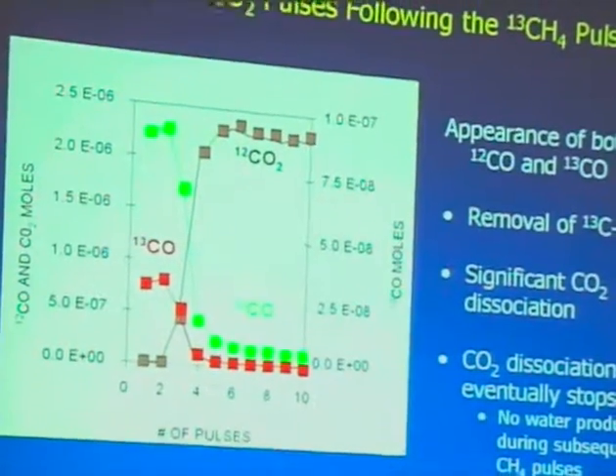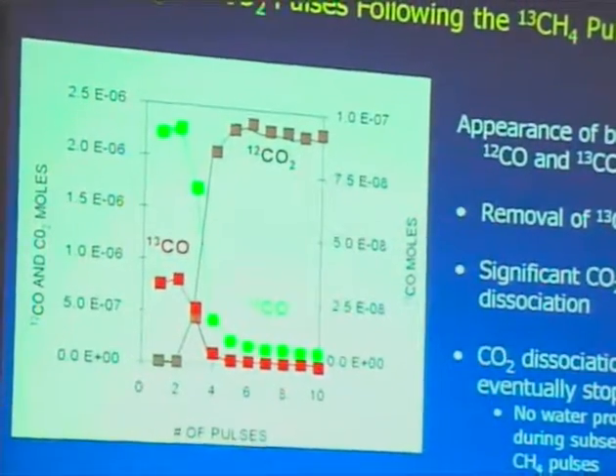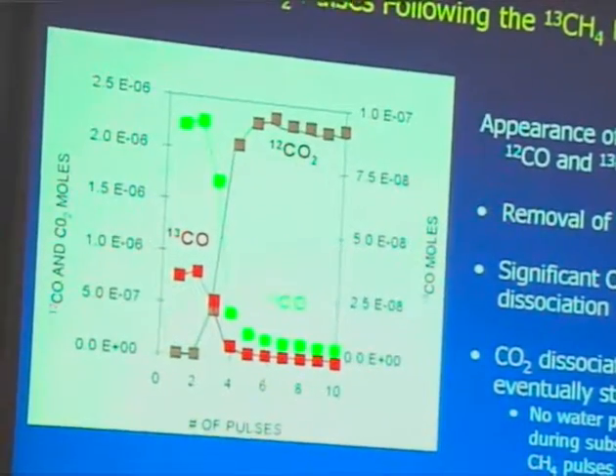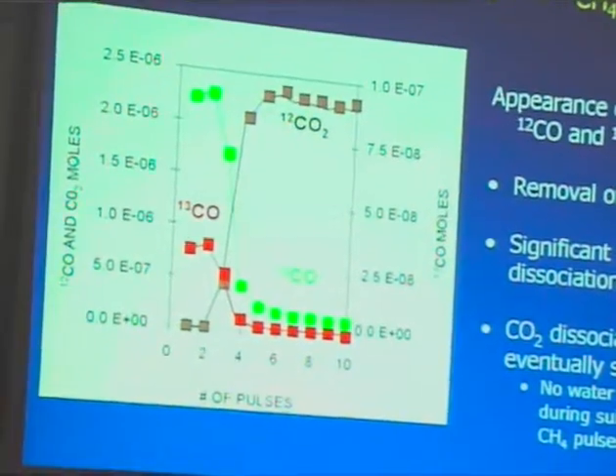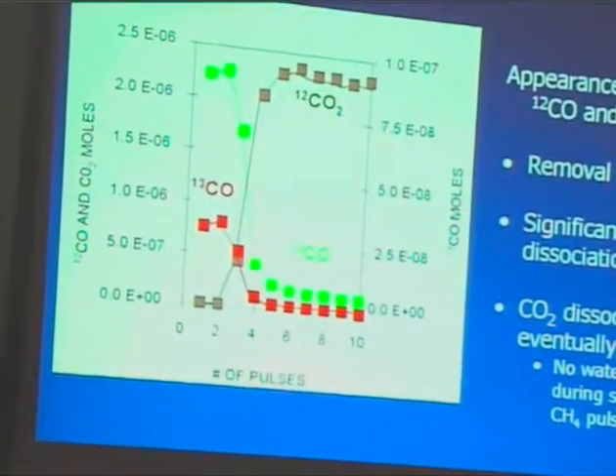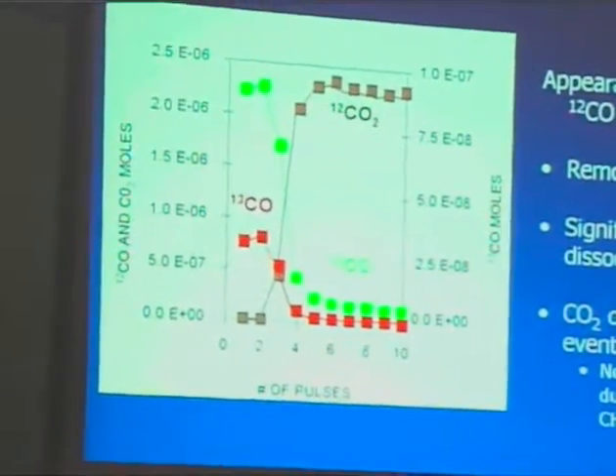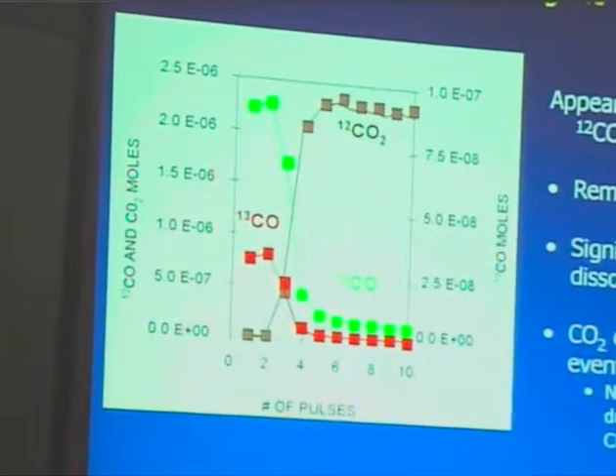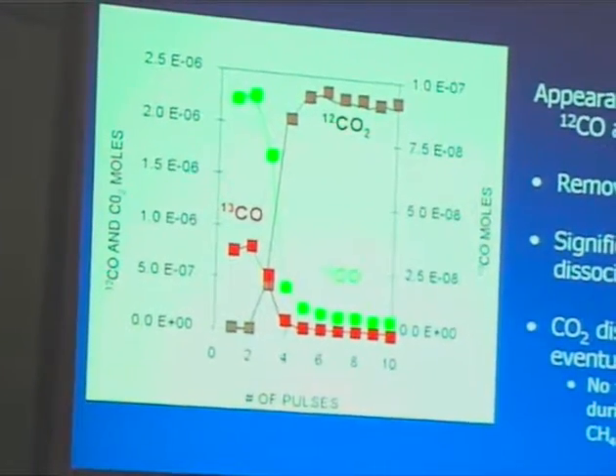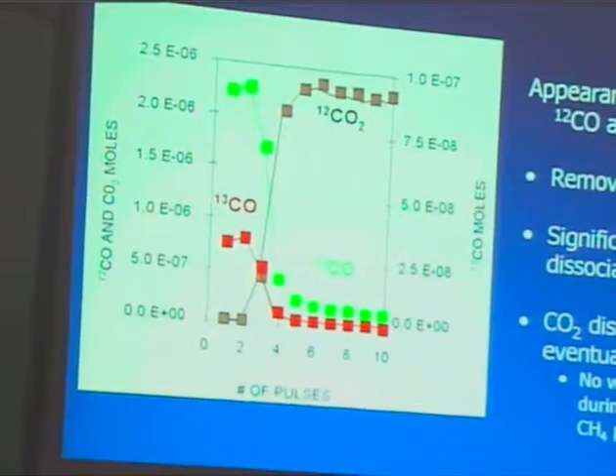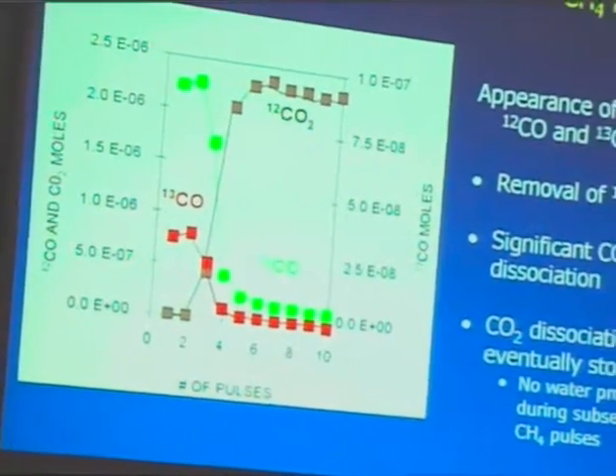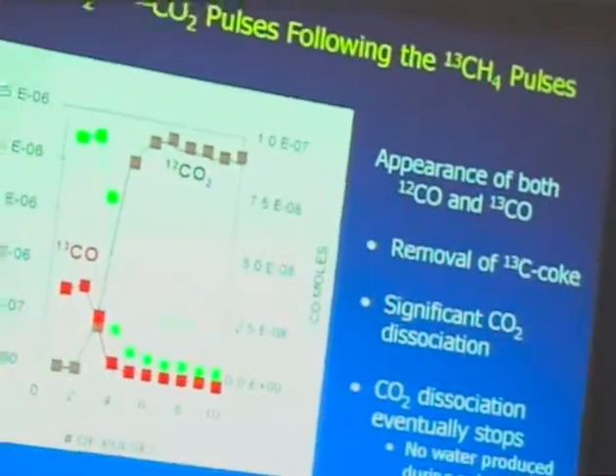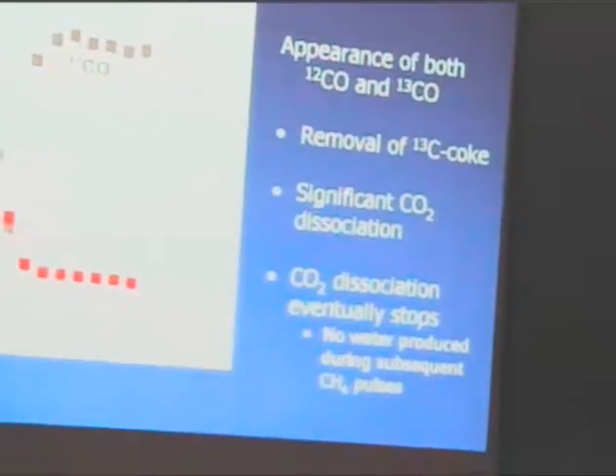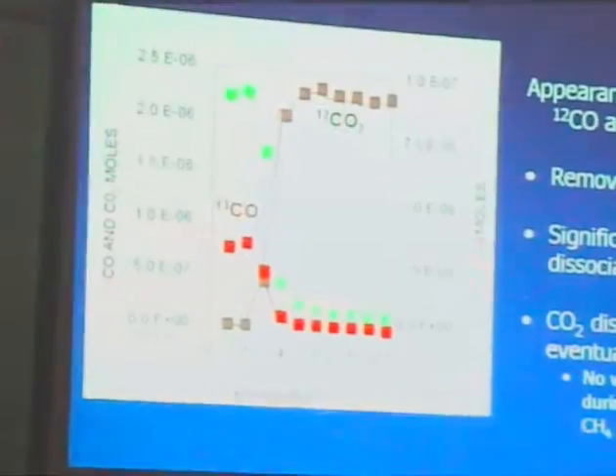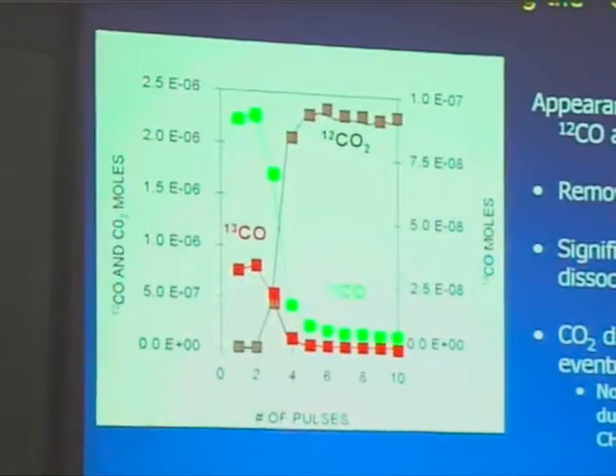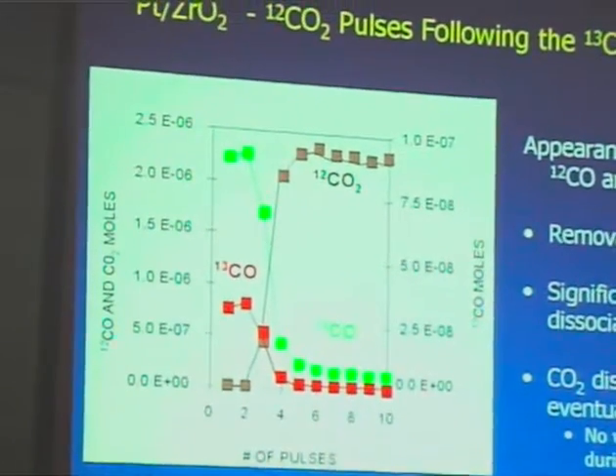We then followed up those pulses with carbon-12 labeled CO2 on the same material, and what you can see is that there's the appearance of not only carbon-12 CO, which would come from dissociation, but there's also the appearance of carbon-13 CO, which would come from removal of the carbon on the metal by the oxygen formed during the dissociation. What we also noticed was that after a number of pulses, the CO2 dissociation stopped.